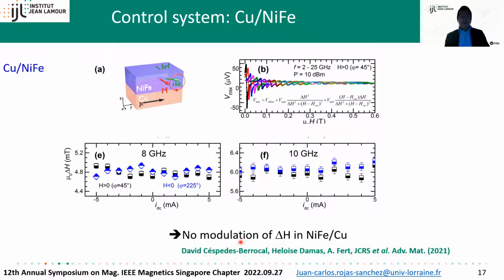In copper permalloy, we do not expect any effect, because copper is a weak spin-orbit coupling material. Here at the top, we have the broadband frequency resonance for this bilayer, and at the bottom, a couple of examples at 8 GHz and 10 GHz. We see that adding a DC bias current, we cannot see any variation of line width. So as expected, it's a good control sample.